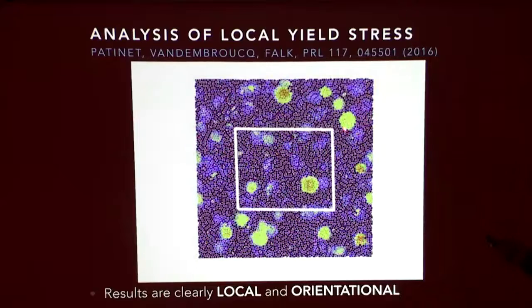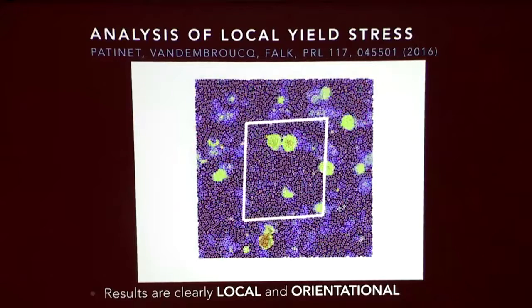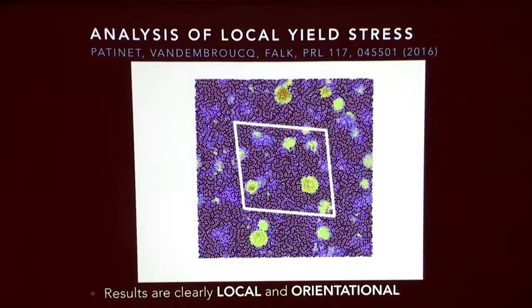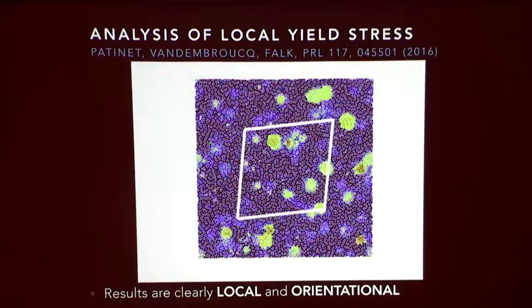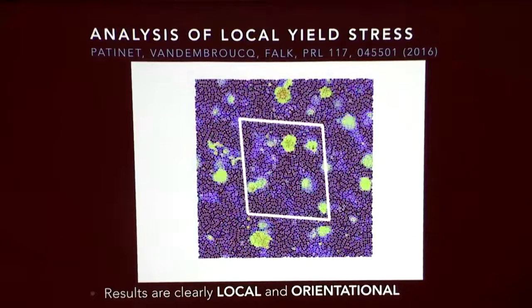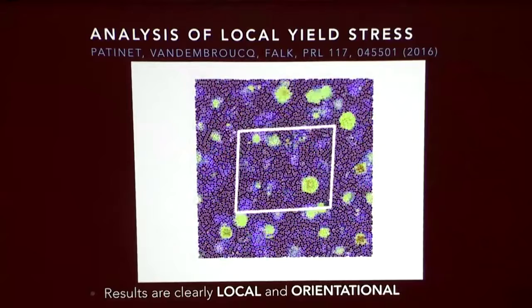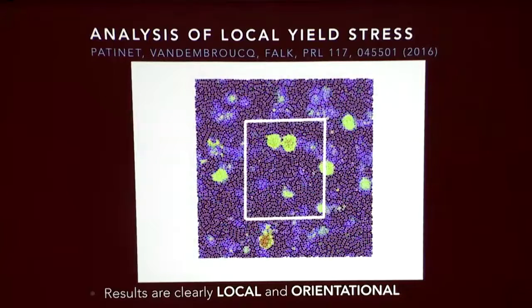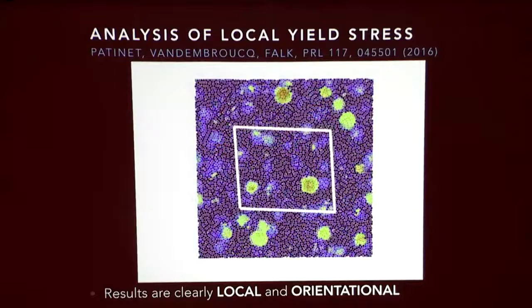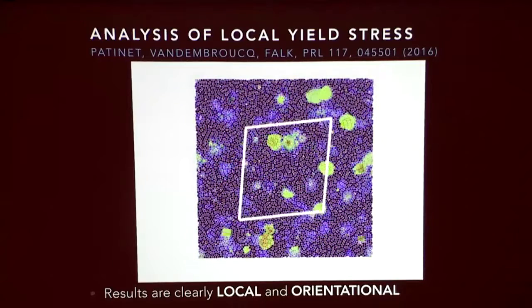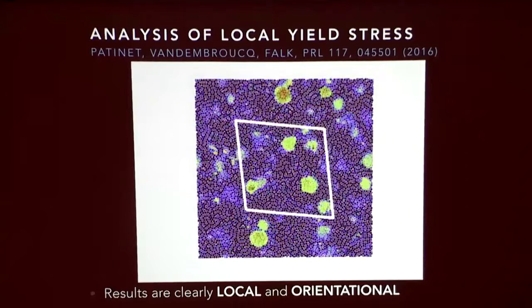You can see that regions highly susceptible to shear in one direction are not necessarily highly susceptible to shear in another direction. These defects certainly have an orientational character to them. So they seem to be both local and they carry orientational information, which is important for storing information like we saw in the Bauschinger effect earlier.